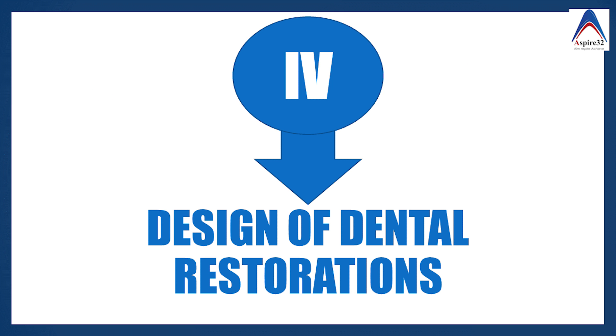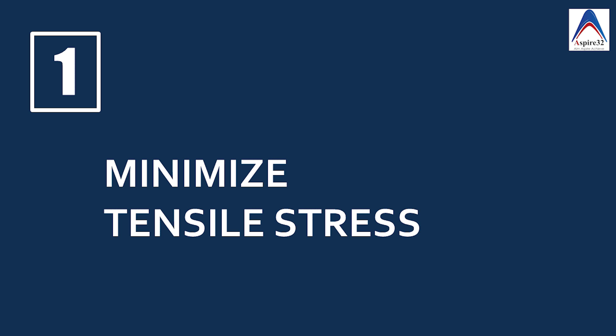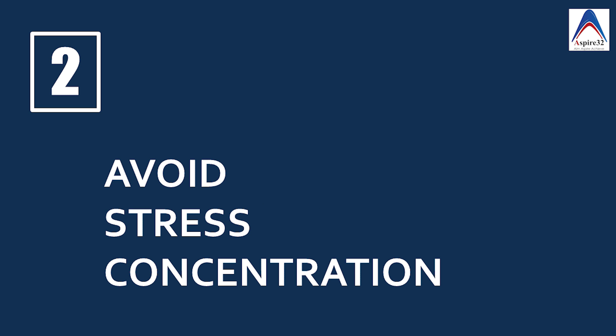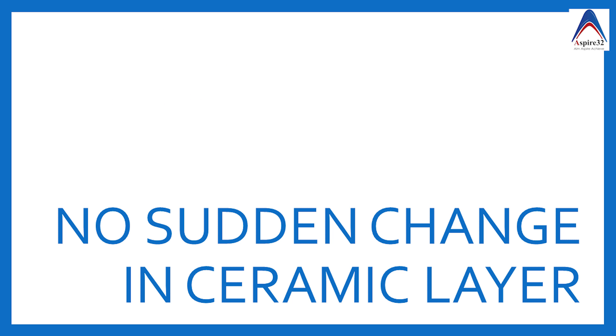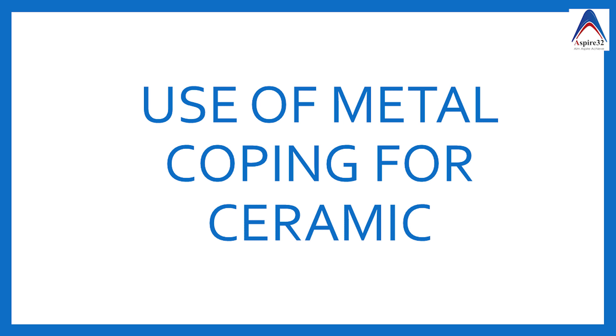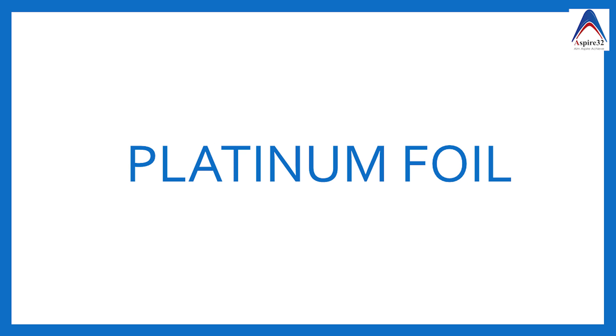The last method of strengthening ceramics is design modification. The restoration must be designed to minimize tensile stresses and avoid stress concentration. This is achieved by preventing any sharp margins in the crown preparation, avoiding sudden changes in ceramic thickness, and using a metal coping to reduce the impact of tensile stress on the ceramic.